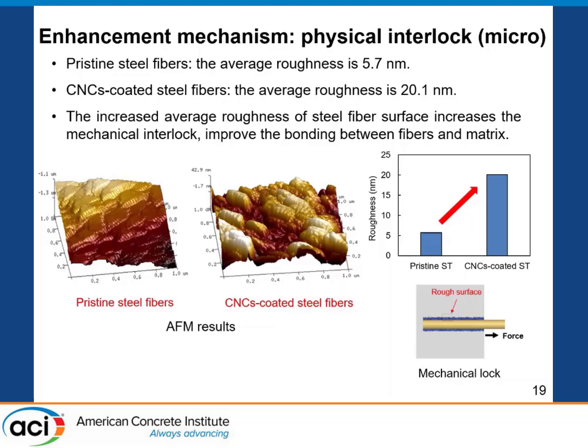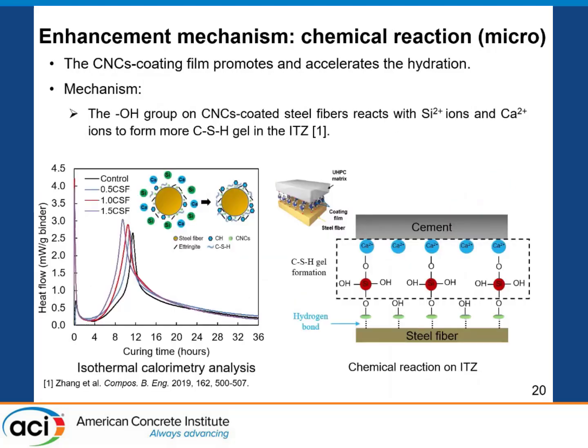One of the reasons is the improvement in the physical interlock. Using AFM testing, we found that the CNC-coated steel fibers have a much higher average roughness than the pristine steel fibers, around 4 times. The increase of the average roughness of the steel fiber surfaces increases the physical interlock, and thus improves the bond between the fibers and matrix. And the good part of the CNCs is that they can also improve the chemical reactions. As they have abundant hydroxyl functional groups, they react with the silicate and calcium ions to form more CSH in the ITZ, the interfacial transition zone.